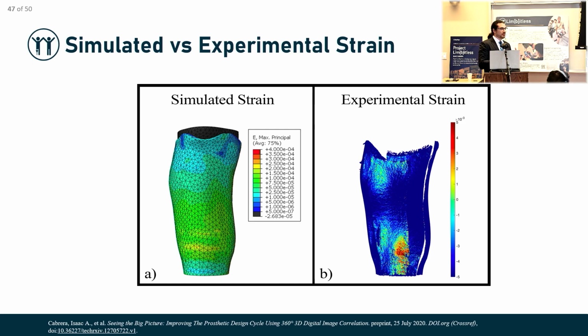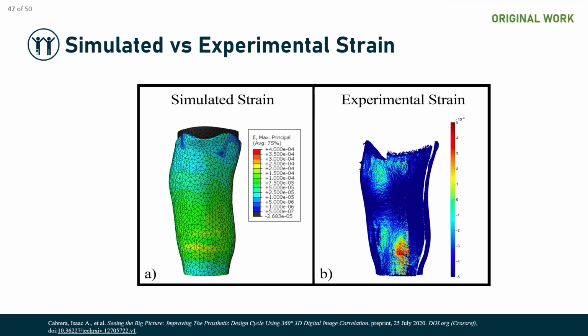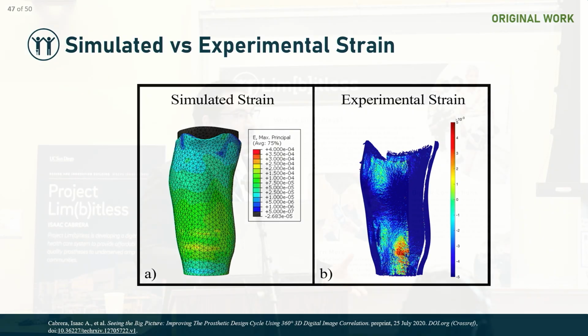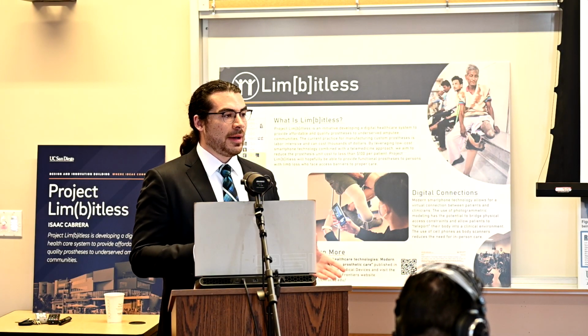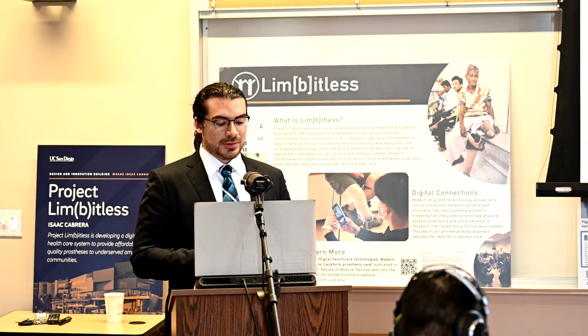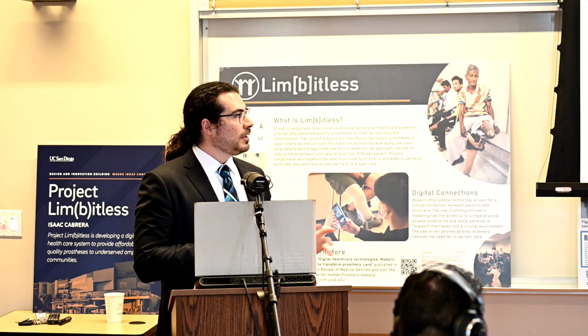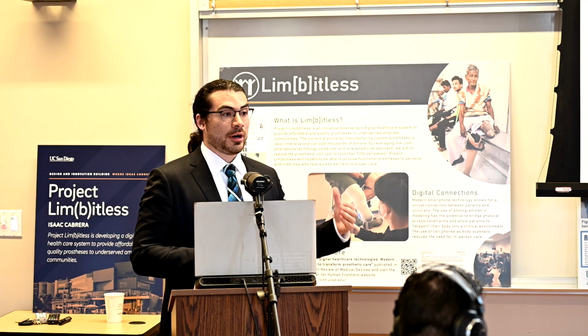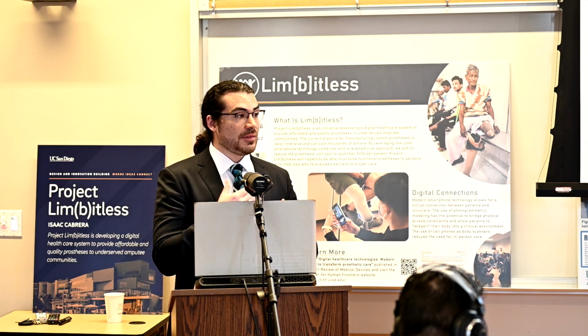So we compared those to some multi-body finite element simulations that we had done, and of course one of the things we noticed right away is that our simulations were off by an order of magnitude compared to our experiments. And so really, what I want you to see from this is that using the technique we developed, we were able to see a problem that, if you had only done simulations, you might have thought would be safe. But a factor of 10 is an order of magnitude when it comes to safety, and that is an unacceptable margin. So my hope is that these kinds of tools will be used more in the field of prostheses for this type of safety analysis.